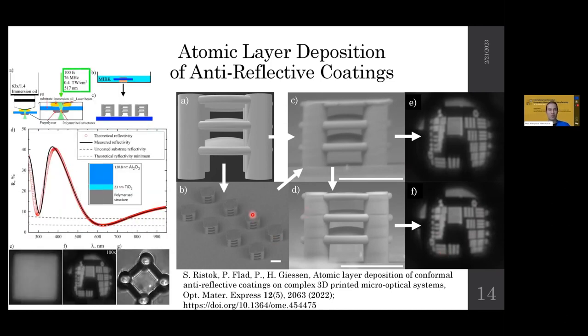And the summary of a protocol on how to produce it is shown here. So the same 3D structuring, developing, then coating. In our case, it was just two layers. So a simpler coating of aluminum oxide coating coated on top of a titanium dioxide coating. And basically, it increased the transparency for visible wavelengths, specifically optimized for red light.